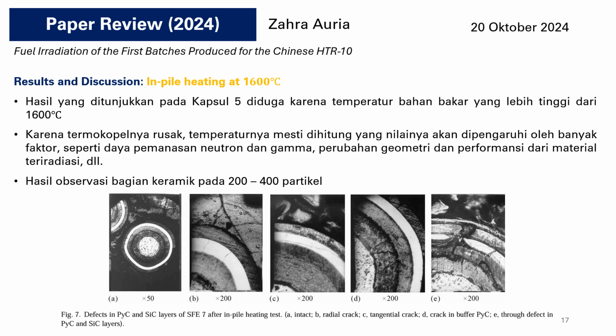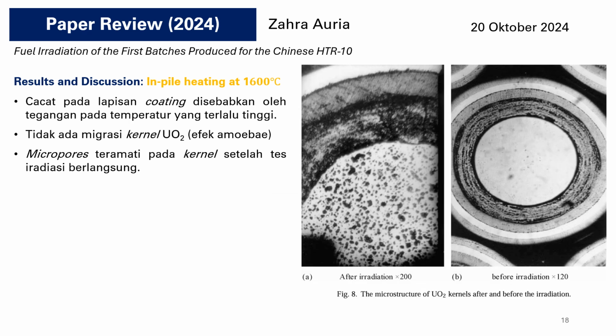These were the observation results for the ceramic parts of 200 to 400 particles. As we can see, there were many defects in the pyrolytic carbon and silicon carbide layers of sample 7 after the in-pile heating test. It can be concluded that the defects on the coating layers were due to thermal stress because the temperature was too high, but there is no kernel migration observed. But we can observe from this figure that there were many micropores in the kernel after the irradiation test was carried out.